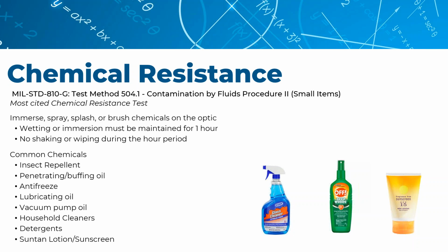So we needed to check the efficiency of our hard coating, and one of the tests that was utilized was an insect repellent test. This comes into play with the machining industry and with the military for penetrating and buffing oil on gun components and things like that. If any of that oil is going to hit the optic, we need to test the optic and make sure that the minute that penetrating or buffing oil hits the optic, it's not going to eat the coating.